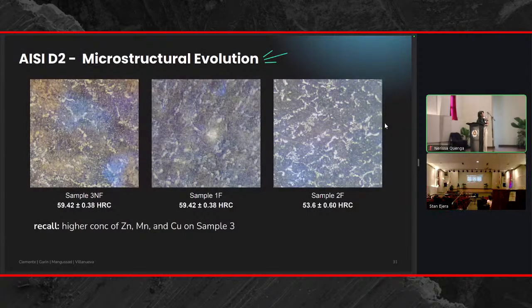And we can see here that since there's a difference in characteristic microstructures between the two failed samples, we concluded that possibly during the production process of the AISI D2 sample, there may have been a difference in tempering and heat treatment, with sample 2F having been over tempered with the presence of more coarse carbides, and as well having lesser counts of zinc, manganese, and copper, because alloying elements also affect the final hardness of the sample.